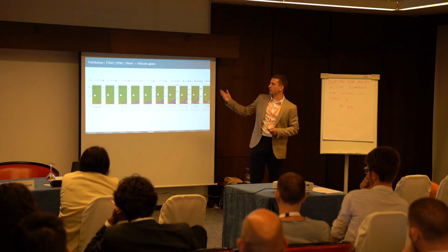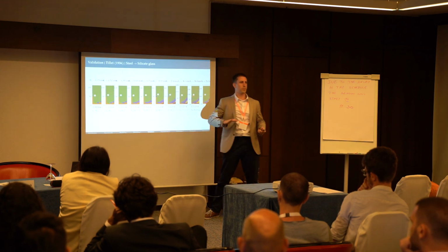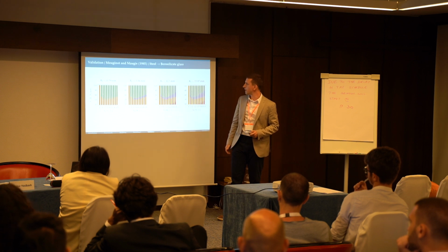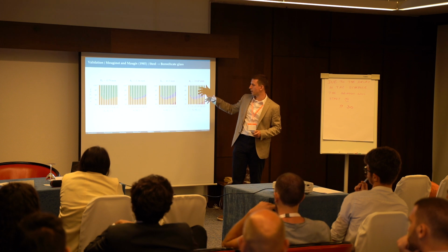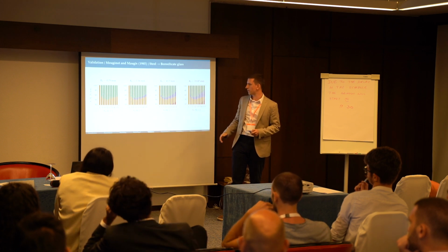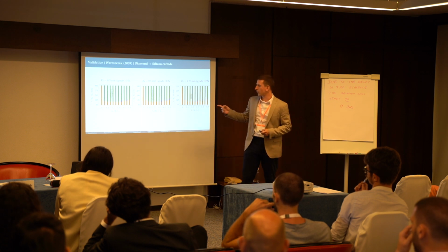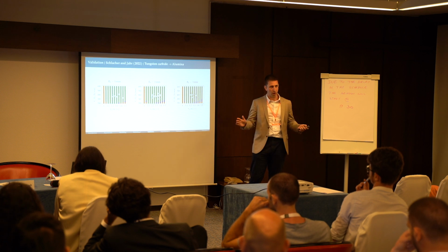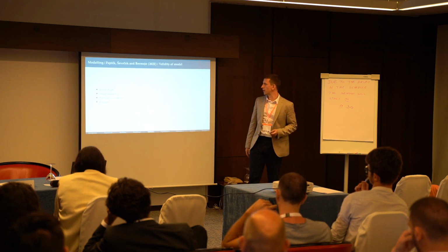So we took the experiments from Tille, and we get no match. We predict half of the forces, so probably not working yet. Then we took the experiments with soda-lime silicate glass. Here we have somewhat of a match, but not really. Then diamond with the silicon carbide, I would say no match. Tungsten carbide with alumina, no match. Tungsten carbide with silicon nitride, again failure.